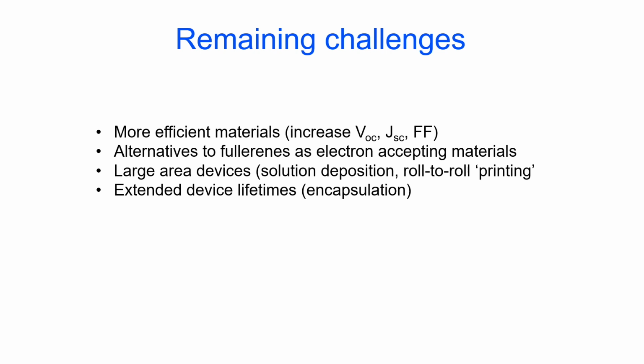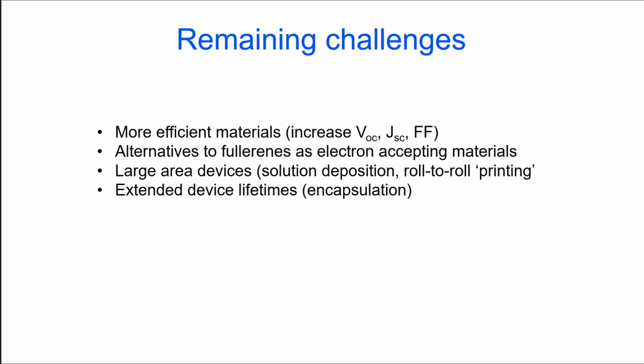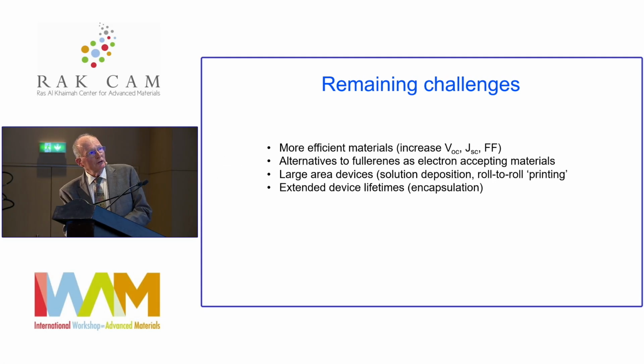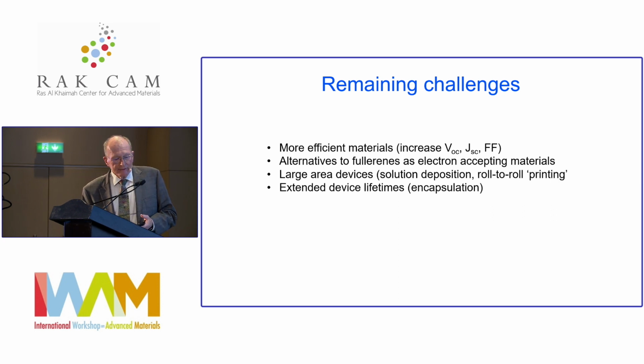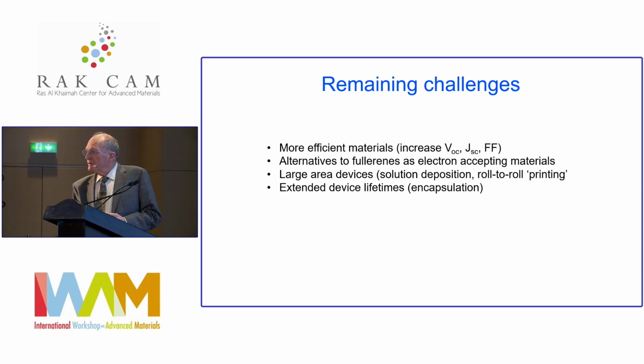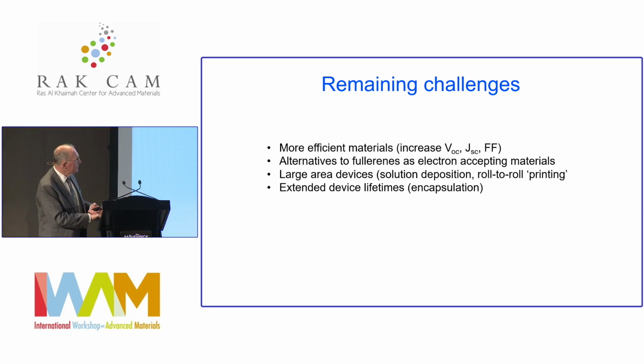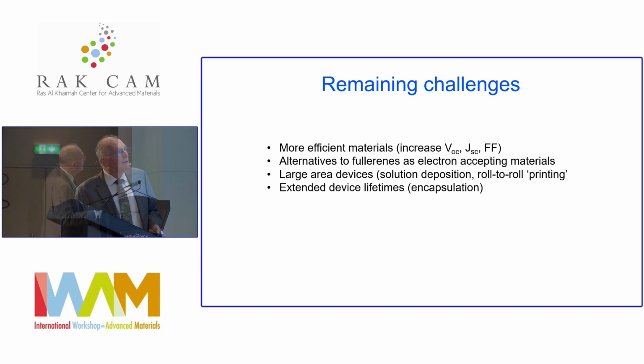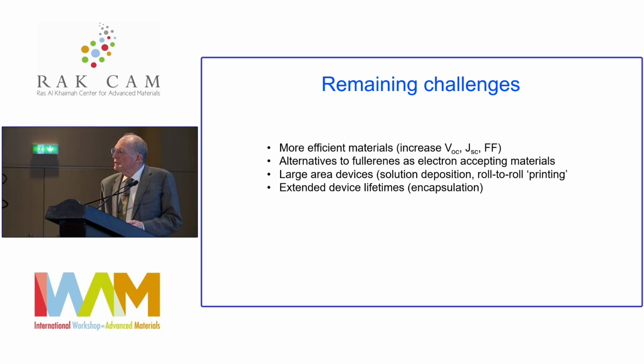So what remains? Well, it remains to get better at everything, really. More efficient materials, so you can improve open circuit voltage, as I said, short circuit current, but the fill factor is the thing one can really work on, and that's related to morphology, it's related to interfaces, and to control in general. And then one would probably want to get away from the fullerenes as a charge accepting material, negative charge accepting material, electron accepting. And ultimately, if this is going to be serious, we're able to manufacture these devices at scale. And lifetimes, of course, are going to be necessary, good lifetimes, in order for these to survive.